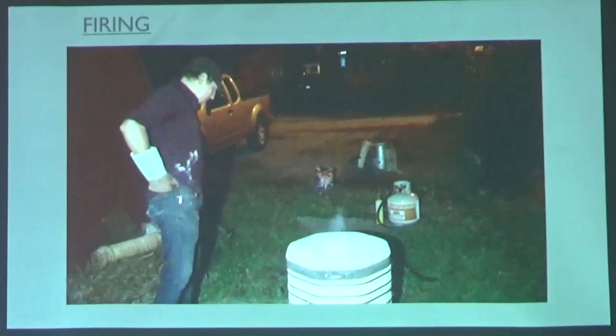Yeah, it is. I want to answer Dan's question again. Quartz inversion is very important, but if you take something that's just recently made and you want to get it through the bisque process, you have to slow that down tremendously. So you couldn't do what Brooke is doing, which is going from cold to 1600 degrees in 40 minutes. You would have to really, especially because before quartz inversion, the physical water has to evaporate, and then there's chemical water that has to evaporate and leave the piece, and that has to happen slowly, otherwise it'll explode.